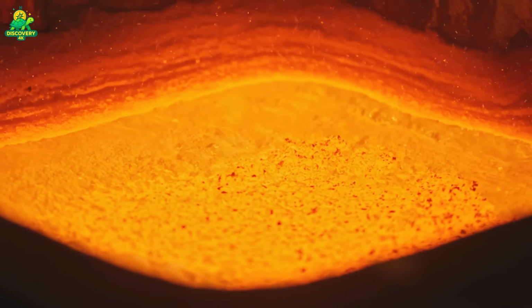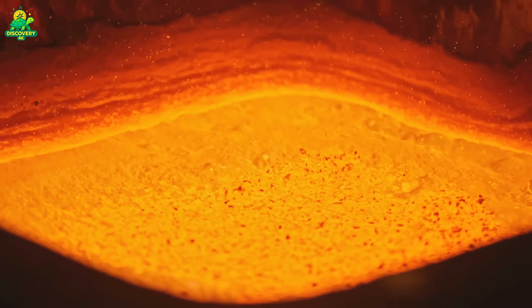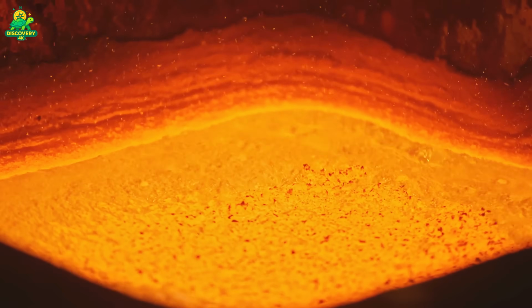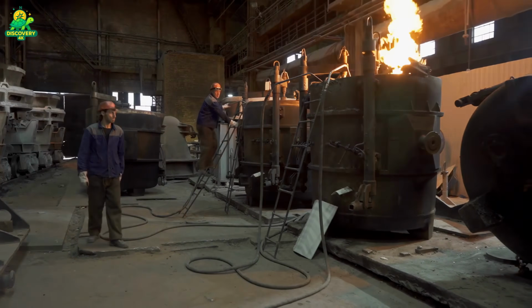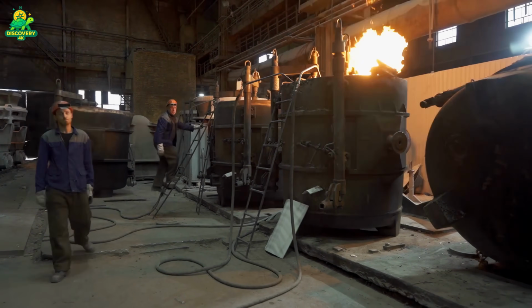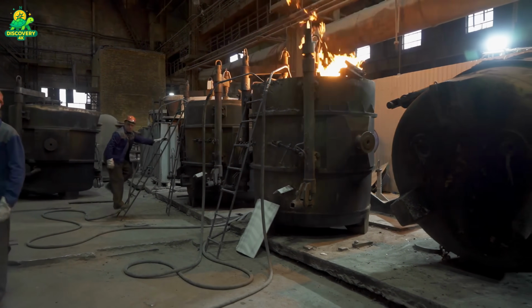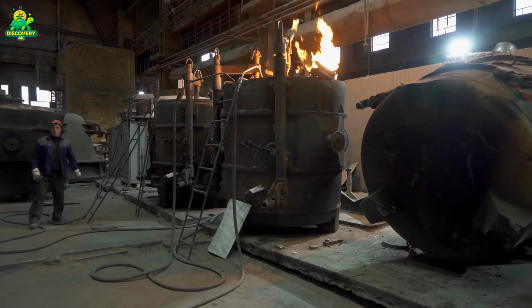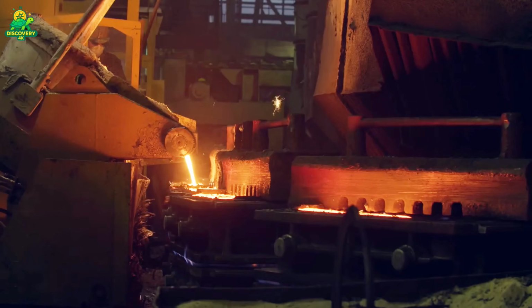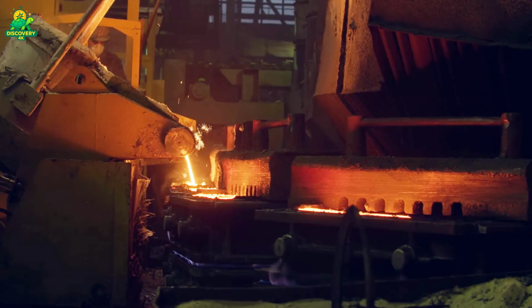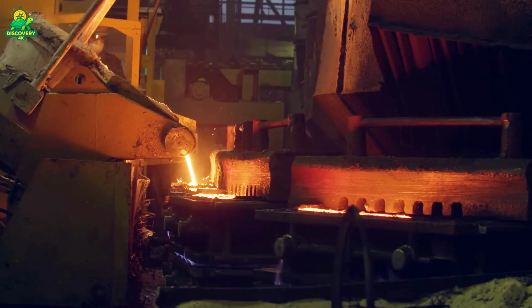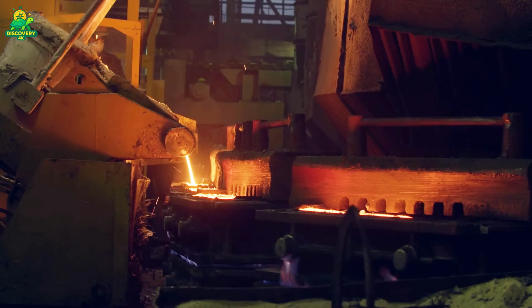The molten matte is then transferred to another furnace called a converter. Here, air or pure oxygen is blasted through the molten material. The oxygen reacts with the remaining sulfur and iron, driving them out as gas or slag. The result, a product called blister copper, so named because its surface appears blistered with bubbles of escaping gas.